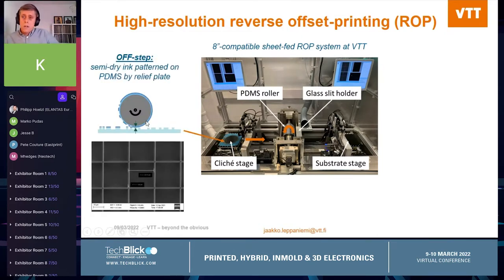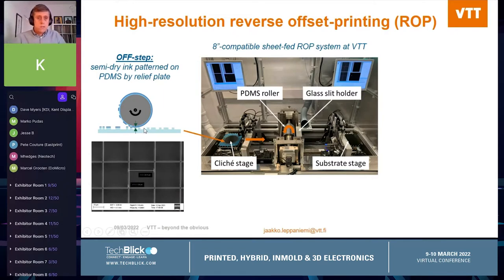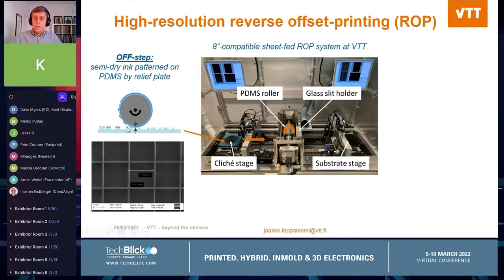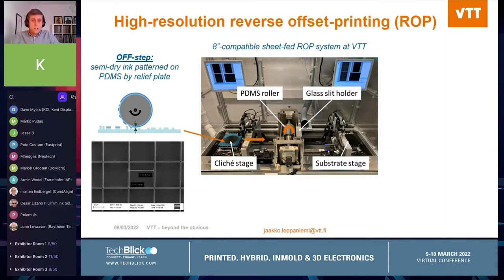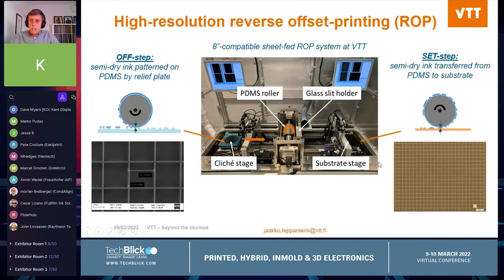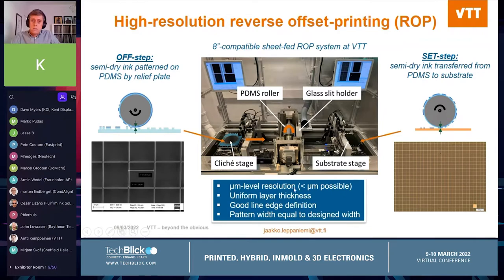Next, in the off step, the semi-dry ink is patterned on the top of the PDMS using a high-resolution printing plate, which removes unwanted portions of the ink from the PDMS. This plate can be fabricated using standard micromachining techniques down to sub-micron resolution. Then, in the final set step on the right, the patterned ink is transferred from the PDMS to the receiving substrate. As a result, micron level resolution with uniform film thickness and good edge definition can be obtained with pattern widths that are close to the nominal sizes. These are features that cannot be typically reached with other conventional printing methods.